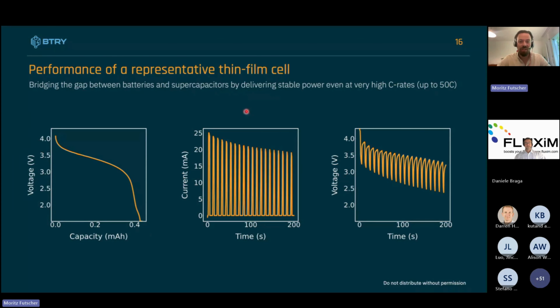And now, how does such a cell perform? In the beginning, I told you that our technology is really in between a capacitor and a battery. We want to share some of our data of one of our cells. Here you see a cell which has a capacity of about 0.4 milliampere hours. But this cell with this little capacity is still able to draw very high currents, in this case above 20 milliamps, which means these are C rates of 50.